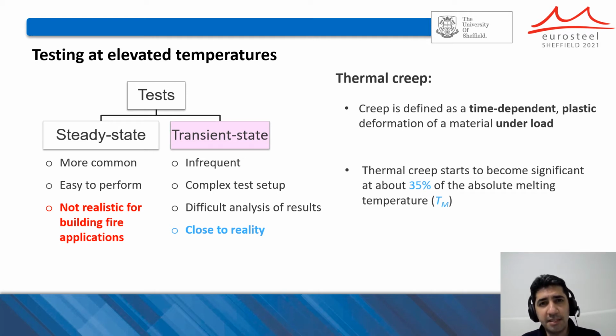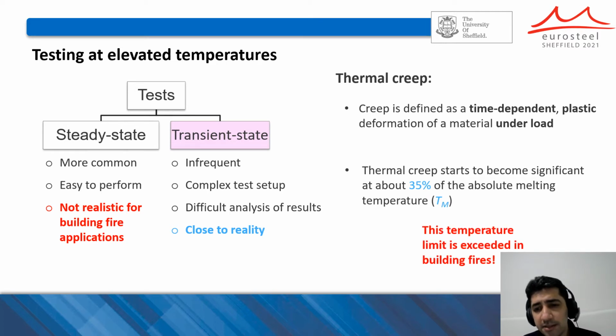One of the complex aspects of the behavior of steels in general at fire temperatures is a phenomenon called thermal creep. Thermal creep is the time-dependent plastic deformation occurring in the material under load at elevated temperatures. For steel materials in general, the thermal creep starts to become significant when the temperature exceeds almost 35% of the absolute melting temperature of steel. And this temperature limit is usually exceeded in building fires.